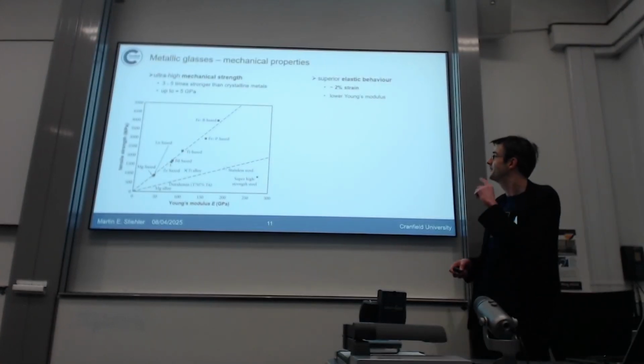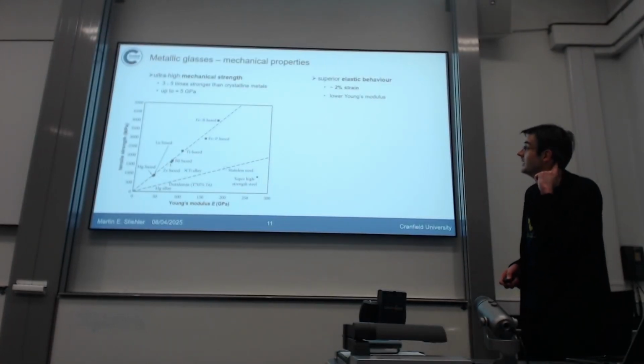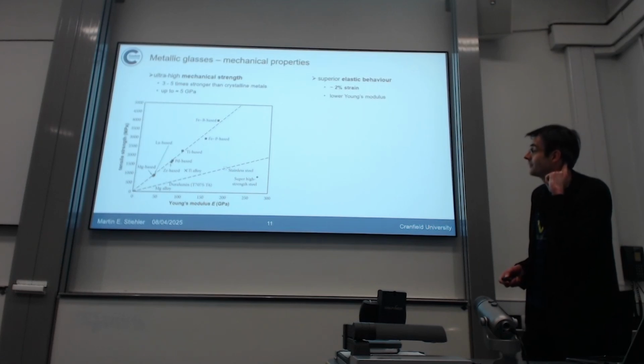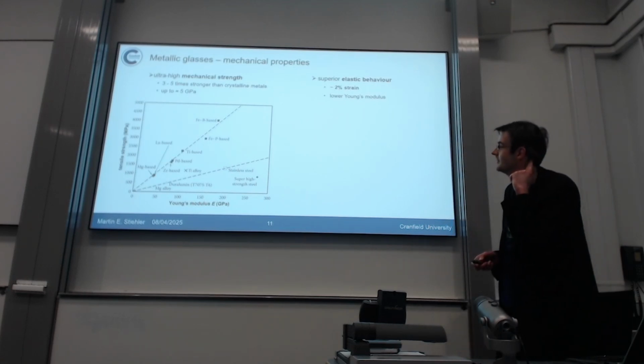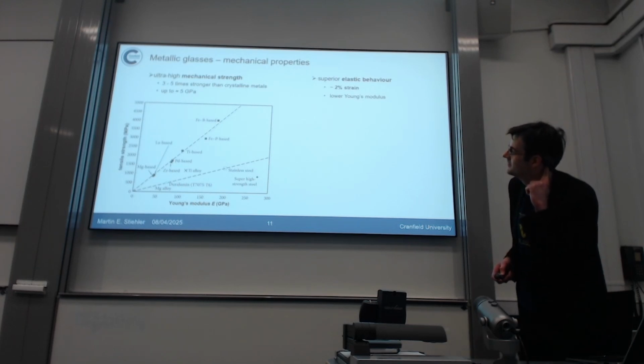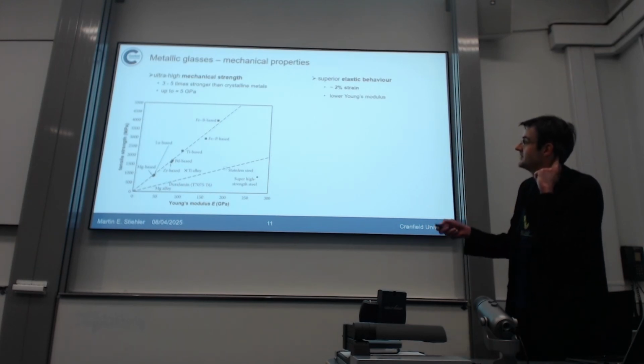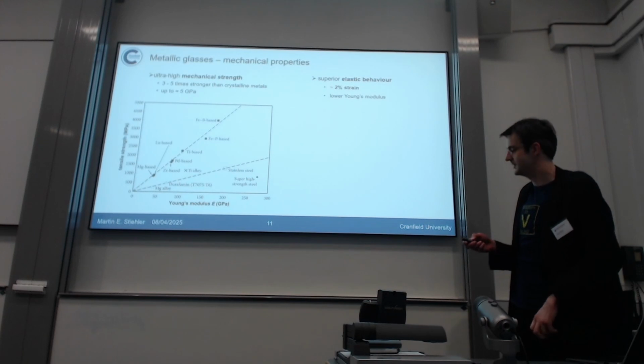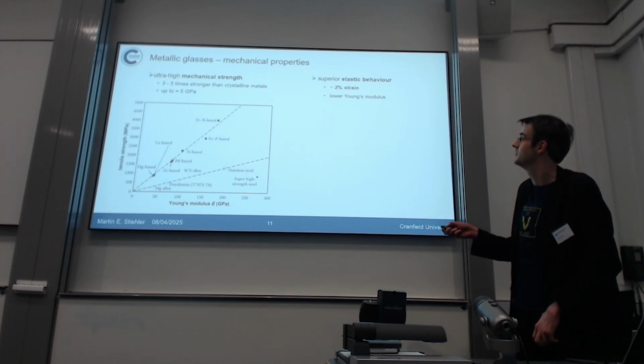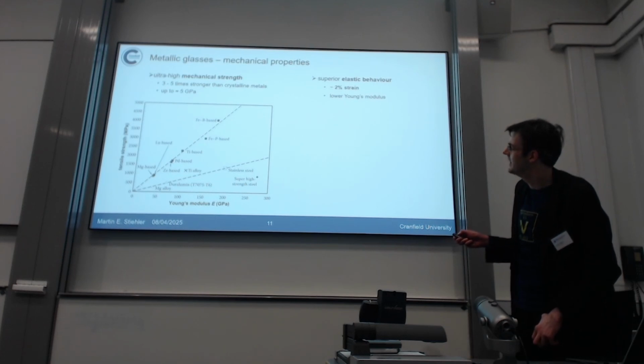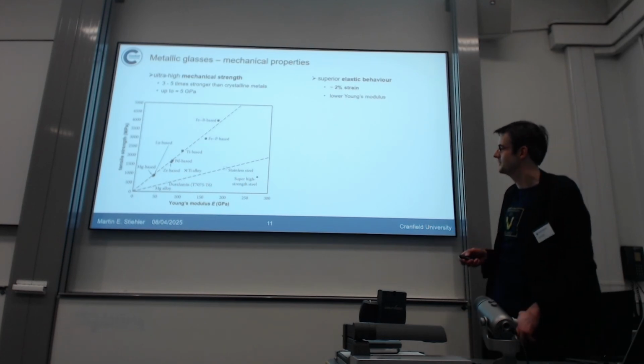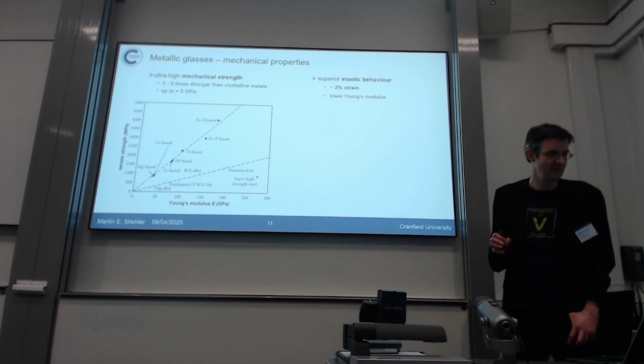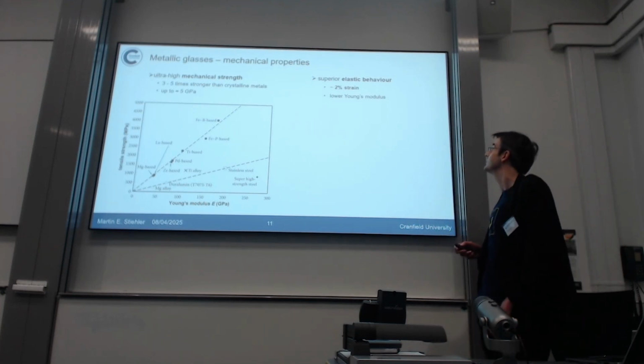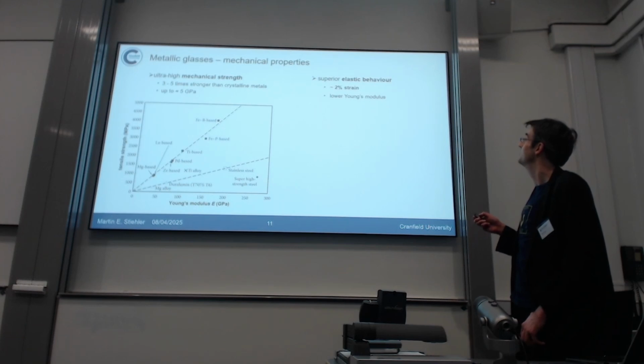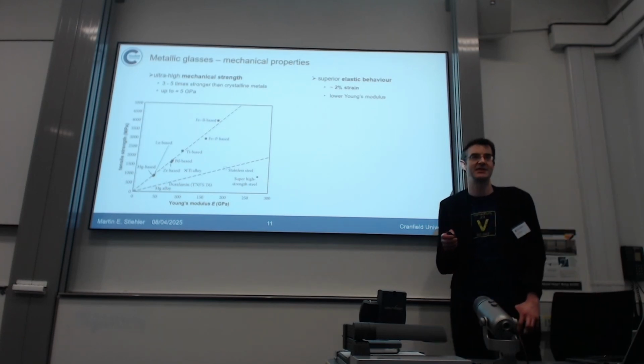Okay, a few of the mechanical properties here. Ultra-high mechanical strength. I selected one of those diagrams. I had planned to show more, but I don't have enough time. This is just showing the tensile strength over Young's modulus. And you see that the tensile strength is much higher compared to crystalline materials here. And what you may see, or maybe not, is that the Young's modulus is actually usually smaller than that of crystalline materials. And in terms of the elastic properties, you have up to 2% elastic strain.